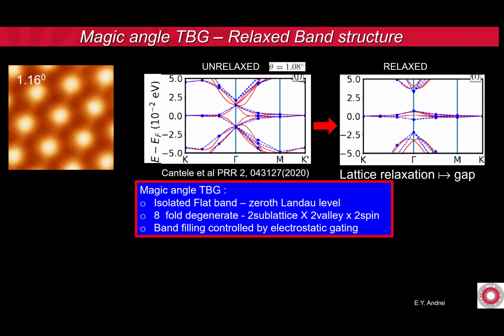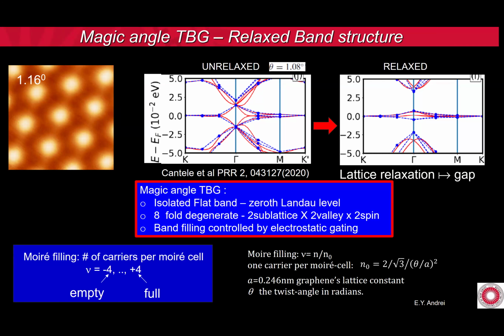The band filling is controlled by electrostatic gating. And this is how we count it. When you have an empty band, when your Fermi level is here, we call it -4. When you have 4 electrons, it's 0. And when you have 8 electrons in the full band, we call it +4. And n here is one carrier per Moire cell, which is inversely proportional to the square of the twist angle.